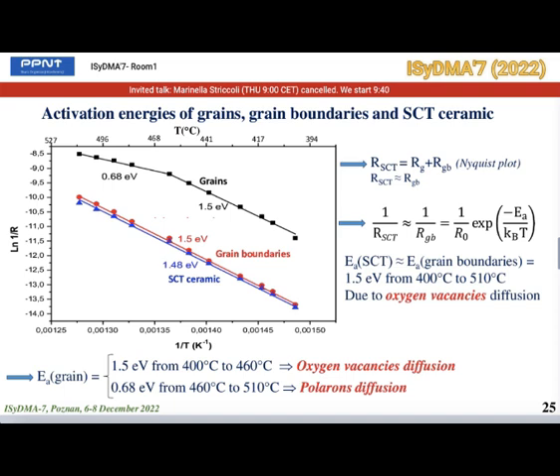Two values of activation energy were found for the grains: 1.5 electron volt between 400 and 460 degrees, corresponding to oxygen vacancies jumps, and 0.68 electron volt between 460 degrees and 510 degrees Celsius, corresponding to polarons.